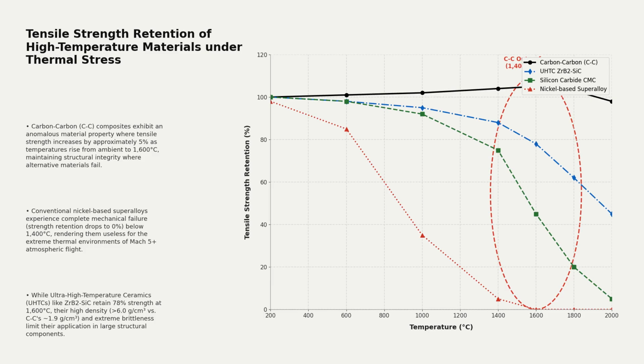Carbon-carbon composites exhibit an anomalous property where tensile strength actually increases at high temperatures. Strength rises by 5% up to 1,600 degrees Celsius. This behavior is unique among structural materials. Alternative materials fail rapidly under these thermal loads. Conventional nickel-based superalloys lose all structural integrity below 1,400 degrees. Ultra-high-temperature ceramics retain strength but are highly brittle and heavy. For nose cones and leading edges, carbon-carbon remains a non-substitutable material.